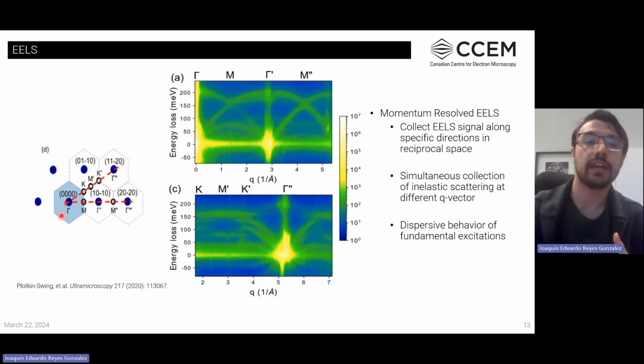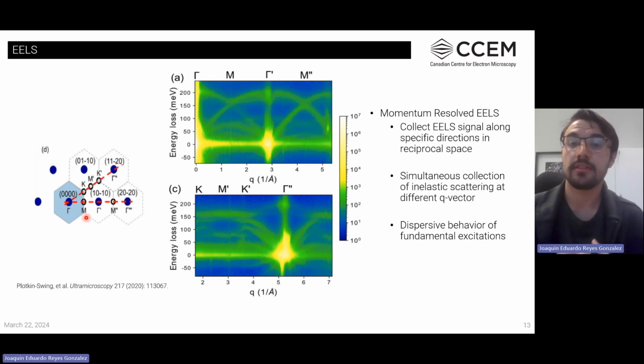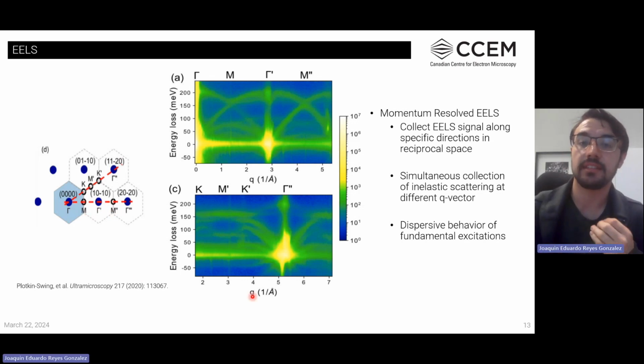For instance, here we have a portion of the diffraction pattern of hexagonal boron nitride, and the rectangular aperture will be located along this direction going from the direct beam to the 1,1,-2,0 diffraction spot, or maybe just to the 1,0,1,0 family of planes, where we can observe the dispersive behavior of fundamental excitations.